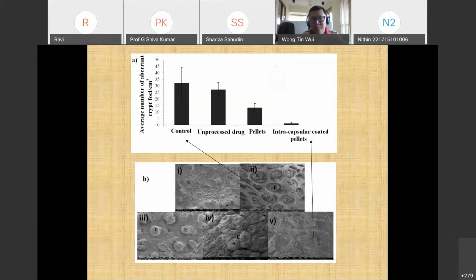Now, what interests us more is the pharmacodynamic performance of intracapsular in vivo coated pellets. Now, these pellets carrying 5-fluorouracil are able to reduce the size and the number of colorectal cancers in vivo. It's also able to bring the histopathological grades of the colorectal cancer back to normal. But what interests most is that 5-FU, 5-fluorouracil, released from intracapsular coated pellets, in addition to combating the cancer growth, can also reduce the aberrant crypt foci found in the colonic region.